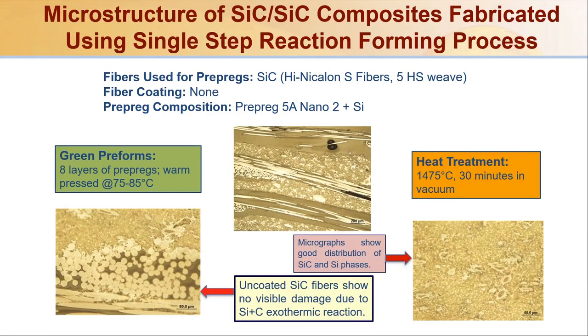The other step we also did, out of curiosity, was to see if we can design the composition and not use any kind of silicon infiltration, and that will basically give you an option. Even if you have very thin fiber coatings, you might be able to protect the fibers. So in this case, we had the 8 layers of prepregs, again warm pressed, and you can see a pretty good distribution of silicon carbide among those fibers. And on the bottom left, even if we just use the heat treatment without any additional silicon there, you can see all those fibers are still intact. That basically tells you that you can use this process, and if you can design the composition properly, you will be able to use very thin fiber coatings and get a very good silicon carbide and silicon carbide plus silicon dense matrix.